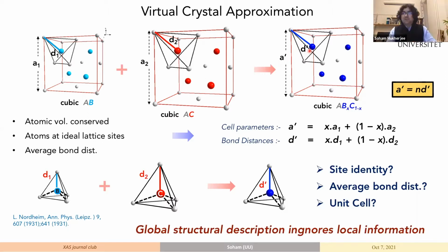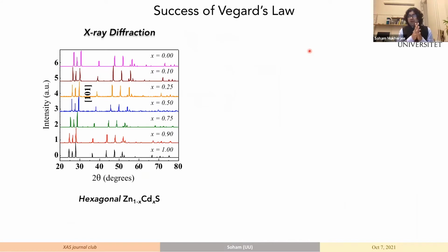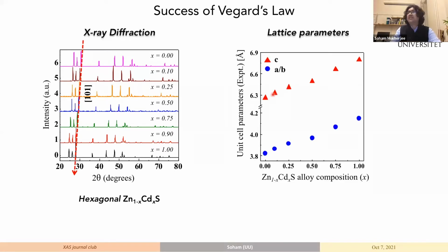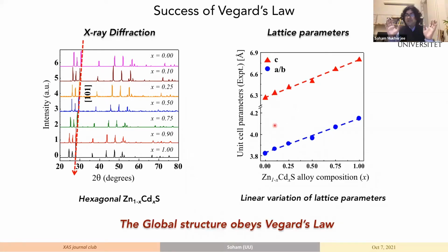So we now go to a particular system, which was the hexagonal zinc cadmium sulfide system, to see how this material behaves when we try to describe the system in a global length scale, which is from X-ray diffraction, and a local length scale, which is XAFS. So this perfectly follows Vegard's law. We see that there is a nice linear variation of lattice parameters, and there is absolutely no ambiguity that hexagonal zinc cadmium sulfide, where cadmium has been doped at the zinc sites, follows Vegard's law, and there is a linear variation of lattice parameters.